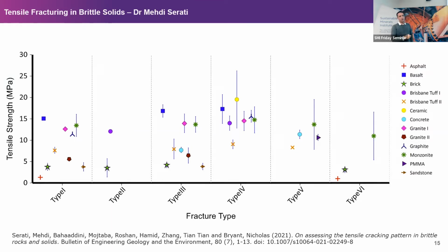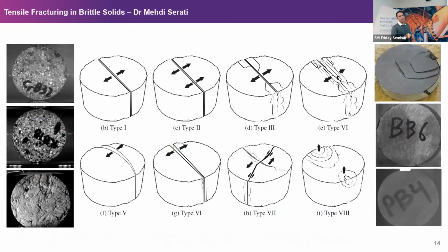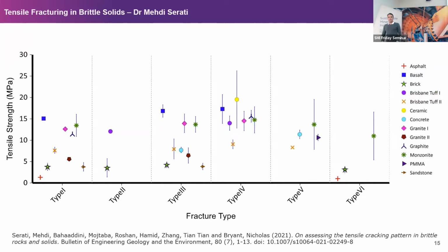The same applies for type 4. It means that in type 4, and type 4 is here, multiple cracking. So if you test your ceramic sample, you don't get a single crack, you use the Brazilian equation, you should expect up to 50% overestimation of the tensile strength. And that's huge, that's huge. So if you are using the Brazilian test to measure tensile strengths of hard and stiff rock, and getting a single crack is very difficult, you need to treat it with caution. Okay, I'm not trying to say it's invalid, because we did it in one of our journal papers and it was rejected because it said you need to be careful. So you need to treat it with extreme caution.